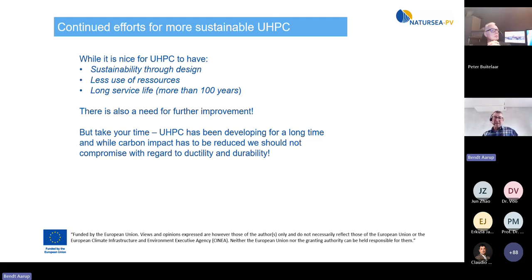we are also aware that because we've had to establish a lot of documentation, we have to be very careful with each step we take. It's very easy to replace 50% of the cement with a calcium filler or slag or fly ash or something like this, but we have to be very sure that we don't reduce durability of our mix, and we don't introduce other problems with regard to fire resistance or anything like this. So it's important that we take very small steps, because UHPC has been developing for a long time.